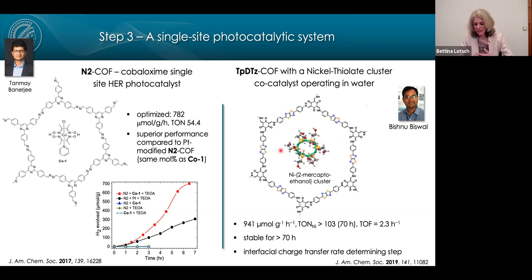And so this can be understood because we don't have any permanent contact between the co-catalyst and the COF, because simply the co-catalyst is in solution. We need collisions between the COF and the co-catalyst for the charge transfer to happen. And so we figured, what happens if we somehow attach the co-catalyst to the COF, or somehow make sure that there is a permanent close contact.